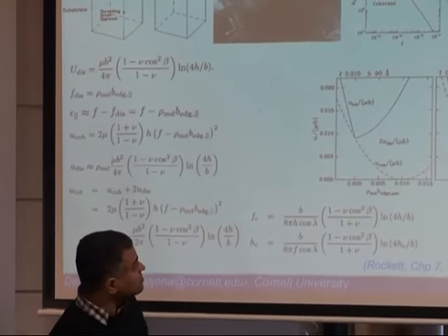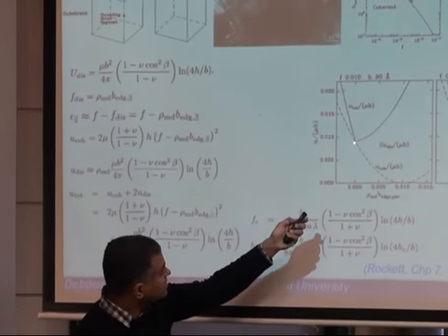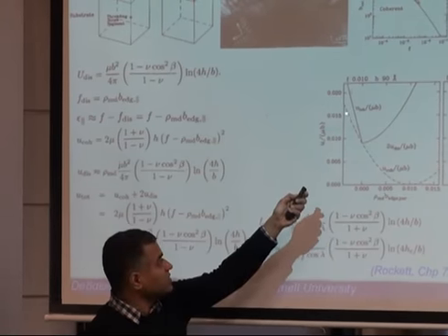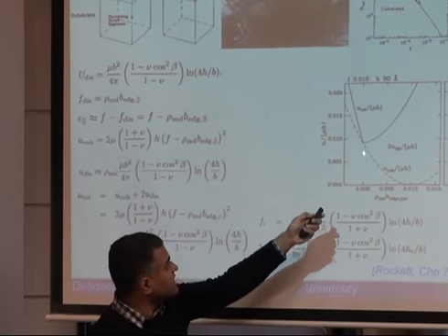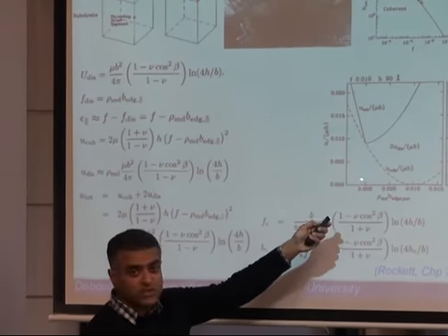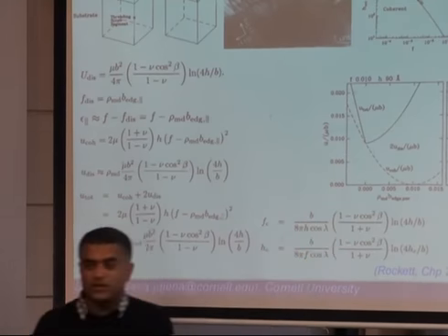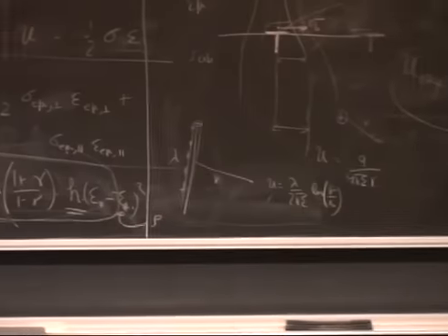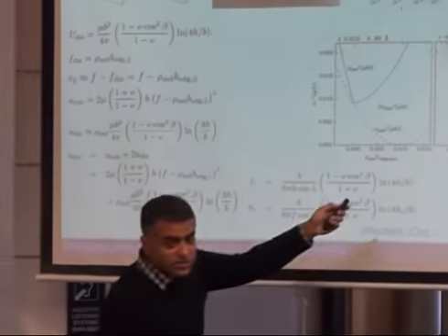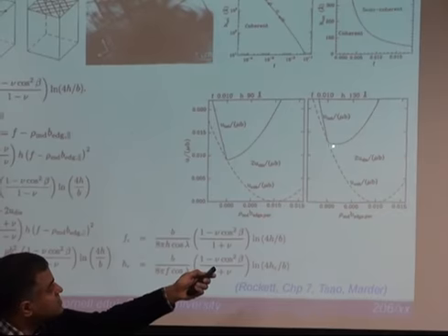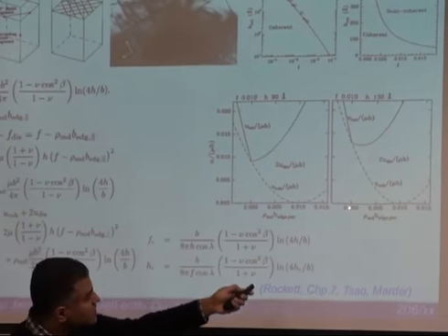And what you see is the minima here is on the parabola. The minima here is at 0 dislocation. There's no dislocations, not a single dislocation. So this remains coherent. This wins, no defects. So as long as you add this thickness, no problem. The moment you go to, say, for example here, 130 angstroms, you see the minima now has shifted here, right? And that means this obviously has formed dislocations now, as you can see.